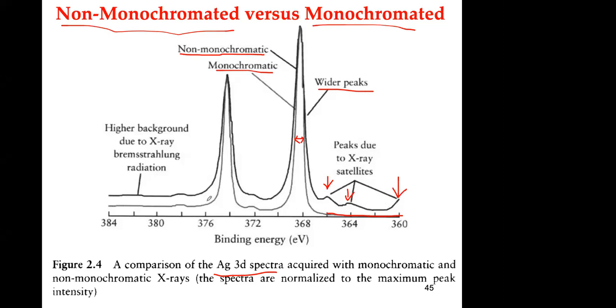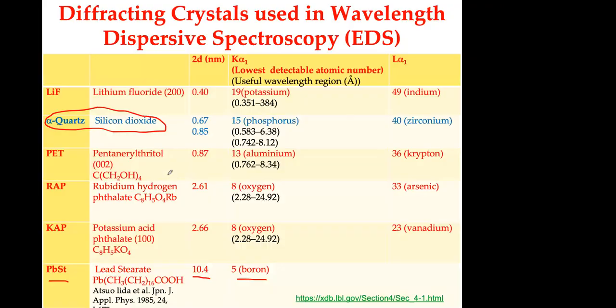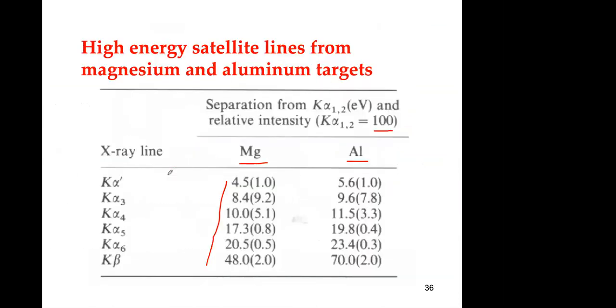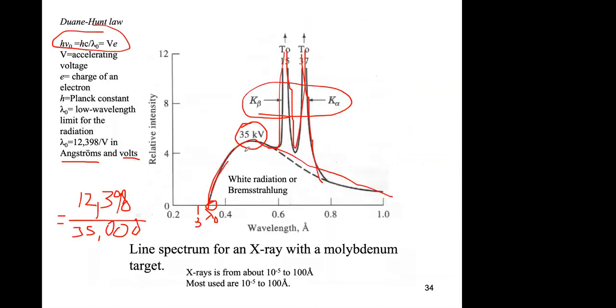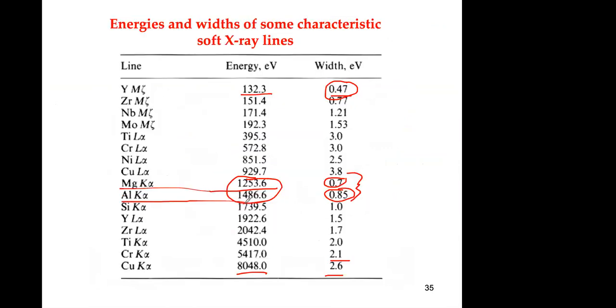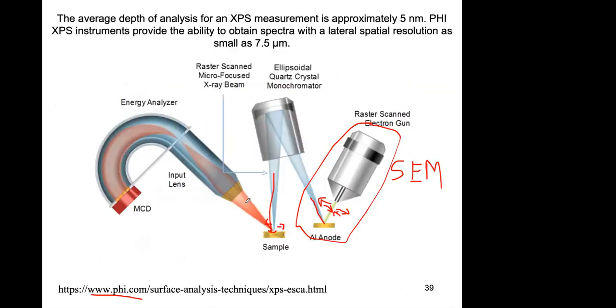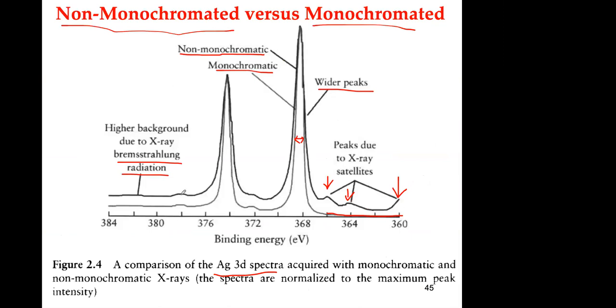So these peaks are satellite peaks that appear. You also have a higher background, and that's because of the bremsstrahlung radiation. Remember that this radiation is also hitting your sample in a polychromatic X-ray source, in a dual anode X-ray source. But when you filter your X-rays, then that background white radiation doesn't hit your sample. So you have other electrons being produced because they were excited with different X-ray energies. That's why the background is higher.